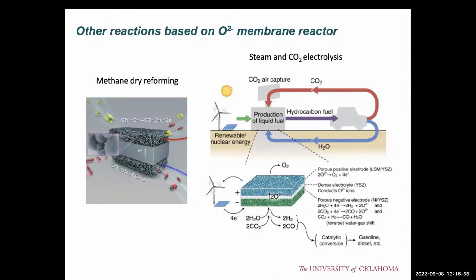Sorry, it's wrong. Firstly, the CO2 is converted into the CO, carbon monoxide, and also the oxygen ion. And the oxygen ion can oxidize the methane to further form the CO and the hydrogen, the syngas. And also we can use it for the steam and the CO2 co-electrolysis.